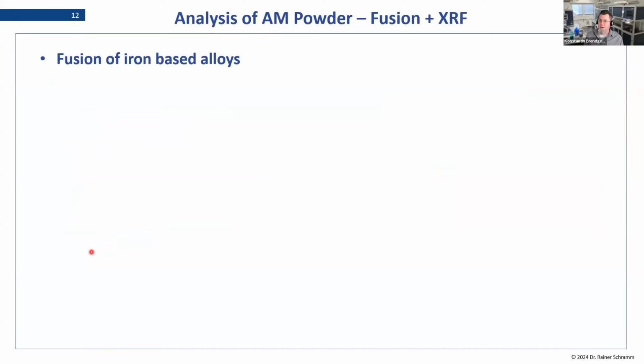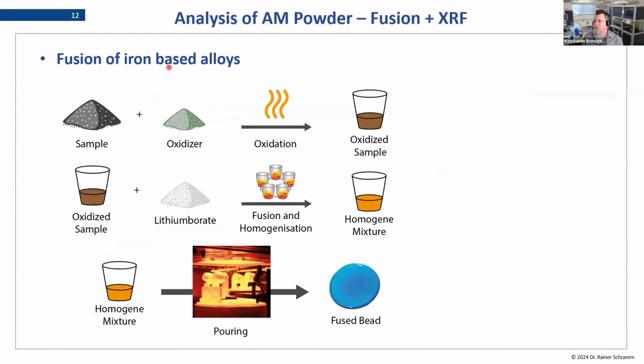Generally speaking, this is metal powder. So in order to make a fusion, we treat it as an alloy. In this case, we were talking about the tool steel, so that was an iron-based alloy. And the idea to do fusion here is to mix our powder sample with an oxidizer, and we do that at a low temperature to get the sample oxidized so it doesn't damage our platinum later on when we do the high temperature fusion. We then mix that oxidized sample with our borate flux, and we then do the fusion process in order to get a fused bead.